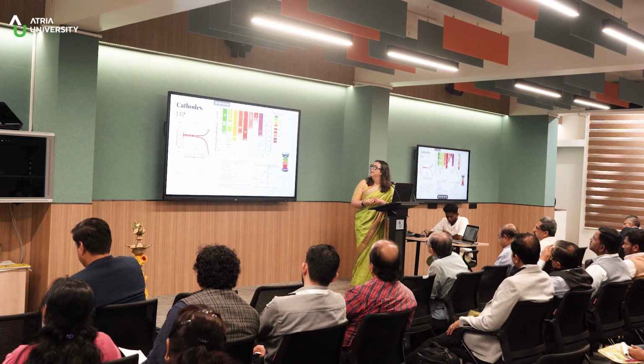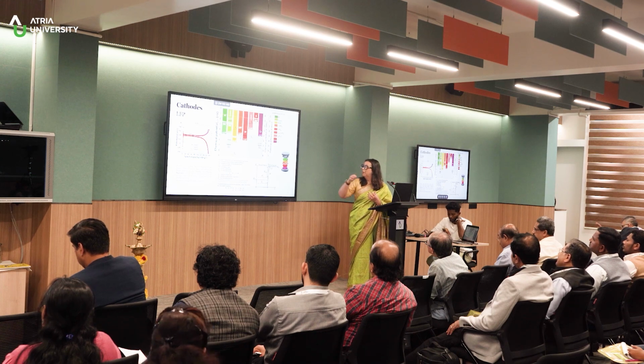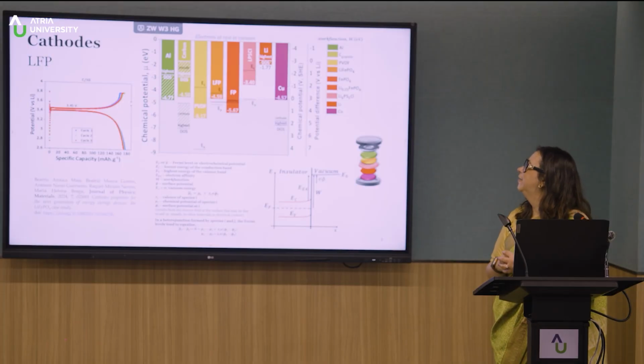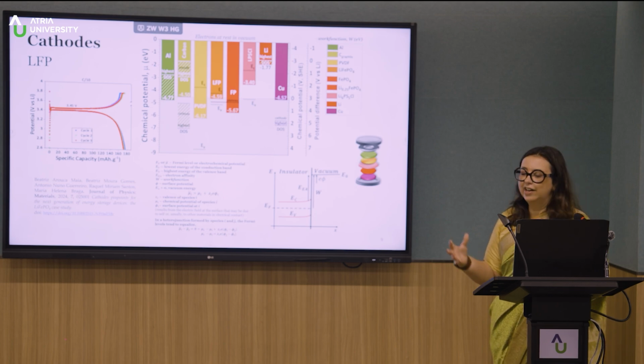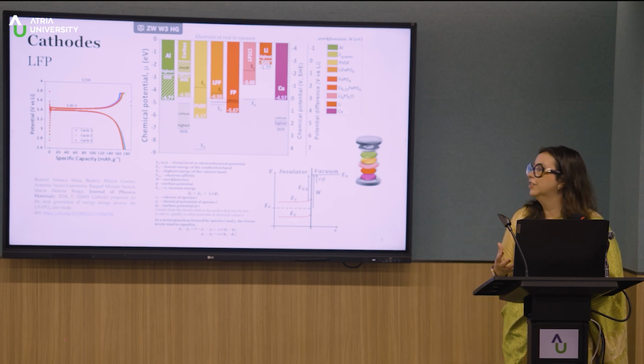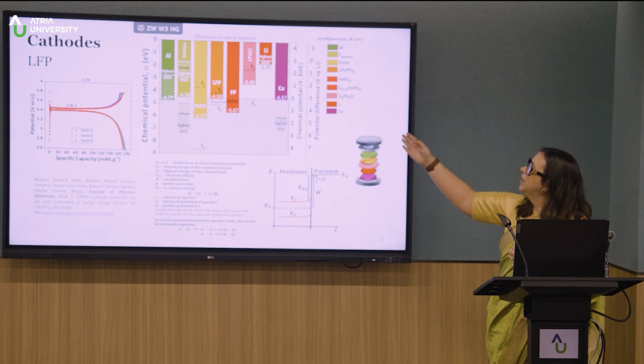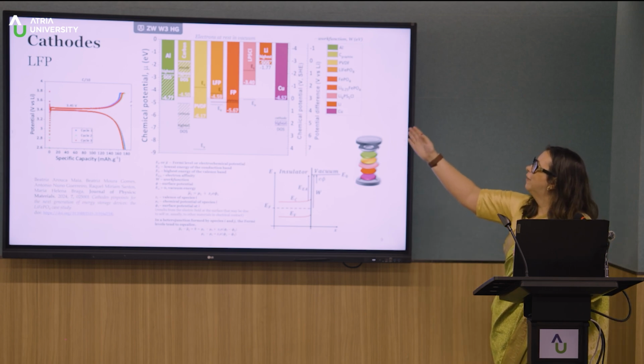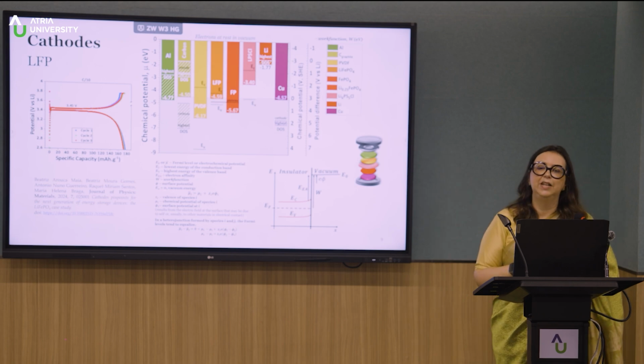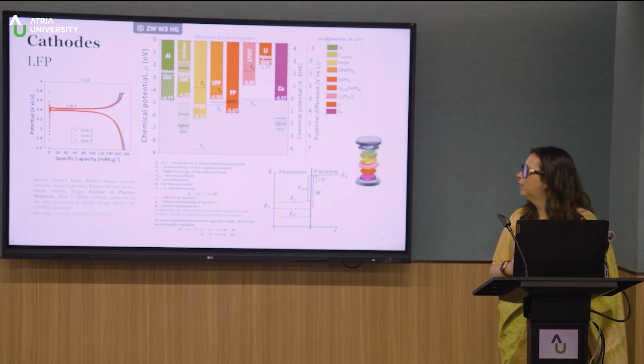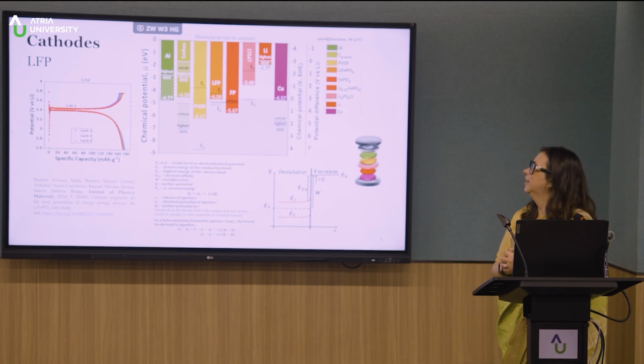And that is not good, because at that time we are making an interface in our cell. But if we can predict this, if we can really know how our materials are going to work, where the valence bands and the conduction bands are, we can figure out solutions on what materials to put in the middle of, for example, lithium and LPSCl. So we wanted to understand this.